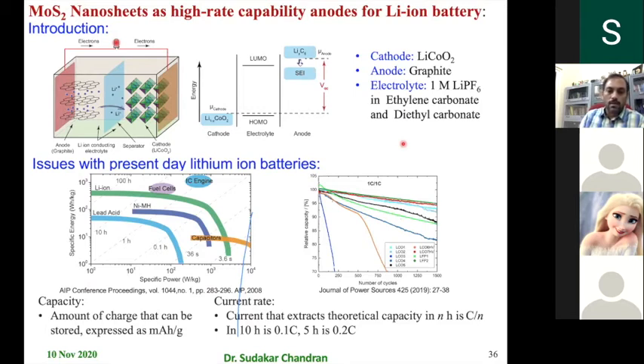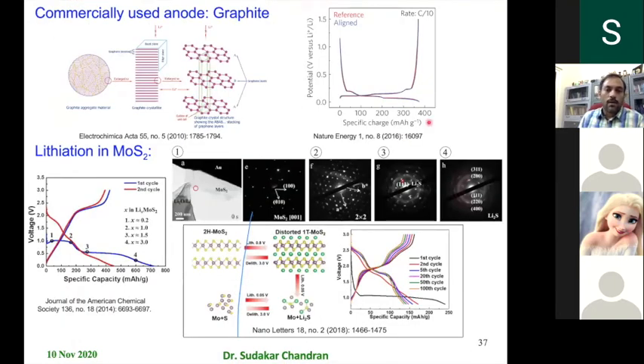So people are trying to address how to get quick charging and quick discharging without losing the stored charge. The other problem is, the graphite, which is the most commonly used anode, has something around 370 milliampere hour per gram of specific charge. And now people are looking for materials that can give much higher specific capacity. For example, silicon was one of the promising compositions, but the problem with silicon is it has a very high volume expansion, and therefore in the electrode it crumbles into powder, and it doesn't work for large cycles. It might work for a few cycles, a few tens. After that, it's gone. So moly disulfide is a promising candidate in that sense.